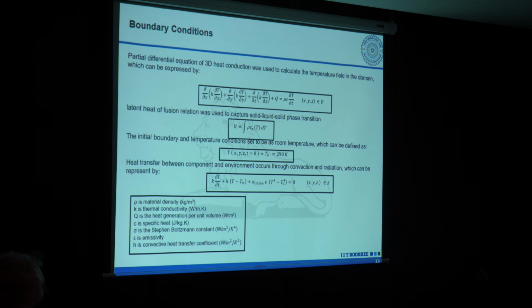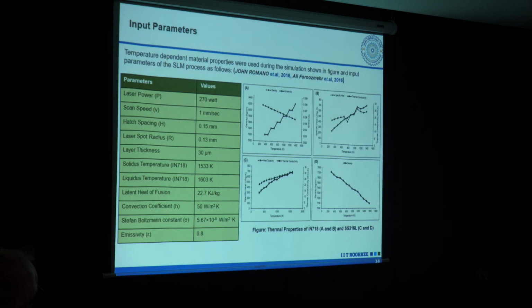These are basically the boundary conditions. We selected the initial boundary and temperature condition to be room temperature, 298 Kelvin, and the heat transfer between the component and environment occurs through convection and radiation. So it can be represented by this equation. Now these are the input parameters that we have used in our setup, and some time dependent properties we have taken from the literature. You see the laser power we have used is 270 watts. These are the parameters that we have used to fabricate these specimens, and a few time dependent material properties we have taken.